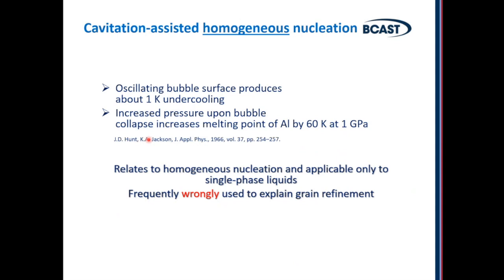One is very fundamental, cavitation-assisted homogeneous nucleation. When a cavitation bubble collapses, as I said before, it actually produces a lot of pressure inside, and this pressure creates undercooling. So increased pressure upon bubble collapse increases the melting point of aluminium by about 60 kelvins, which means that effectively, if you look at the ambient temperature, the melt is locally undercooled by about 60 degrees, which is a lot. So that's going to create homogeneous nucleation sites.